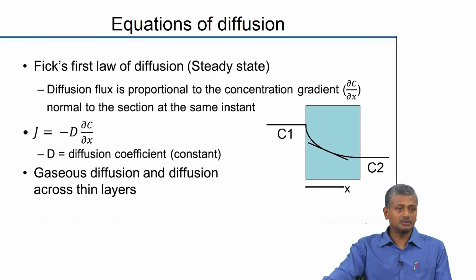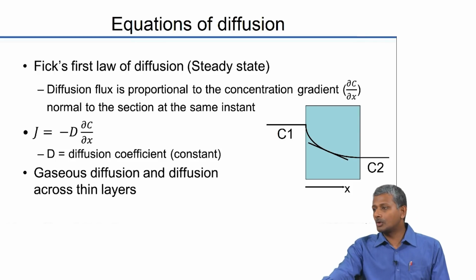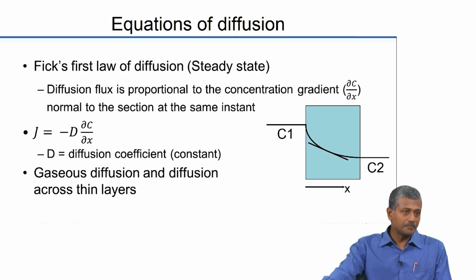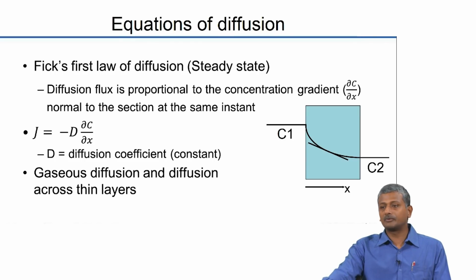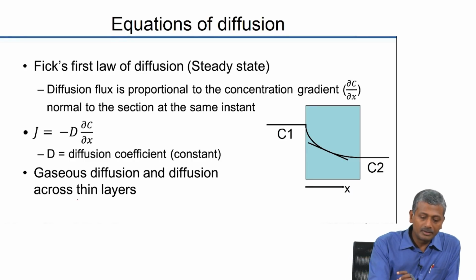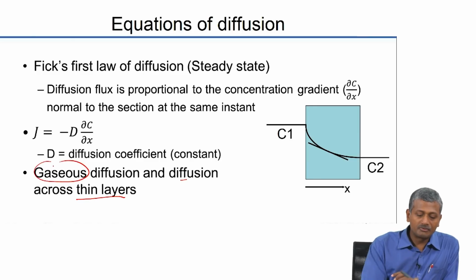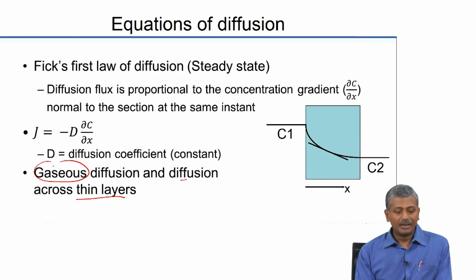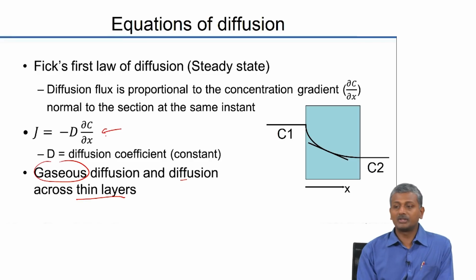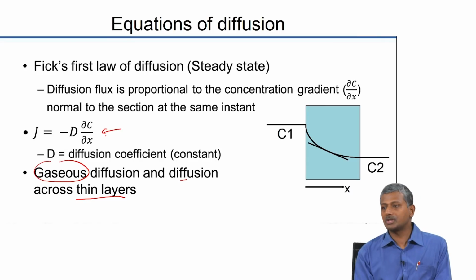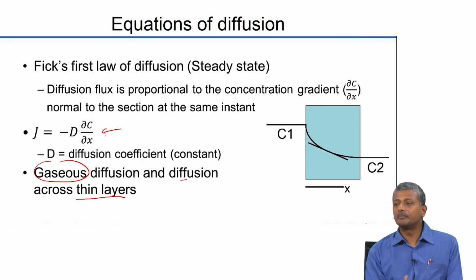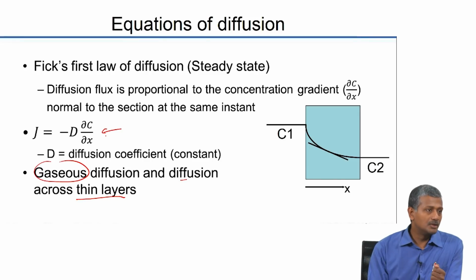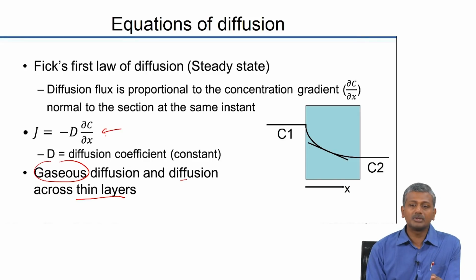One is steady state diffusion, where the properties of the material do not change with respect to time. That means when the concentration gradient is the same, its variation across depth of the material will still be the same. And this is applicable to very thin layers and especially when you have gaseous diffusion happening through the system, okay. And this is defined by Fick's first law of diffusion, where the diffusion flux J is related to the concentration gradient through a proportionality constant, that is your diffusion coefficient. So the material characteristic that you need to evaluate to understand the resistance of the material to diffusion is the diffusion coefficient D, okay.